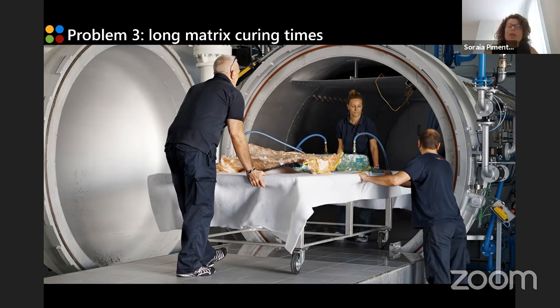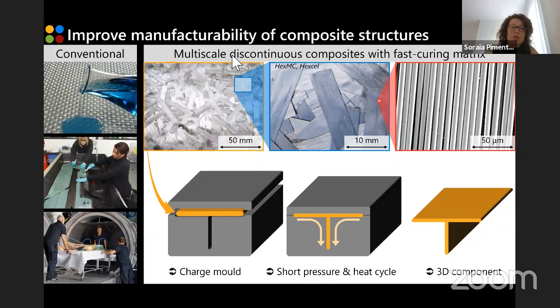So what we can do using discontinuous composites is, instead of using this conventional process that you can see here on the left-hand side in summary, to use multi-scale discontinuous composites with fast curing matrices. So basically the type of materials that I'm talking about has a microstructure that you can see on the top. So at the smallest scale, you have several thousands of fibers very well packed and aligned in the same direction. These make tows, as we can see on the image in the middle, and these tows themselves are discontinuous and randomly oriented inside our structure.